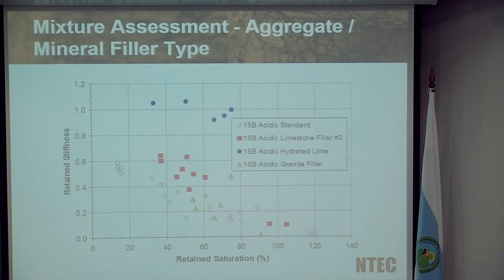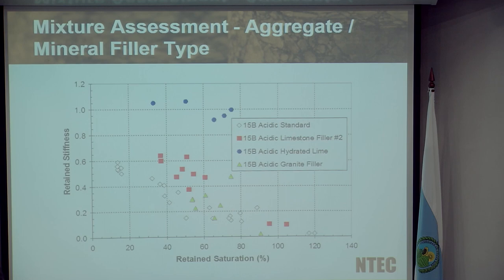So if you look at the horizontal axis of that particular graph, you can see not only have we got retained stiffness on the y-axis, we've got retained saturation. And retained saturation, very simply, is how much water or moisture there is in the particular material. And so instead of testing at one constant amount of water in terms of our laboratory testing, we can range or we can vary that retained saturation level. And the data presented in this particular slide is for a series of